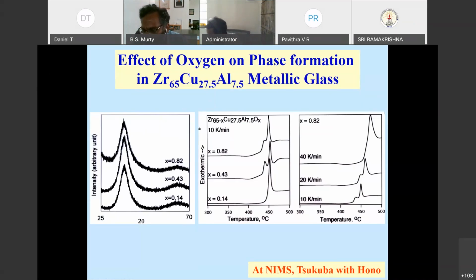So people had always confusion, what is happening inside? Then I had a hunch that possibly oxygen is playing some role. So what we did was we produced 3 different types of glasses exactly with the same composition overall, excepting that the oxygen content we varied in the alloy. There are ways to do that.